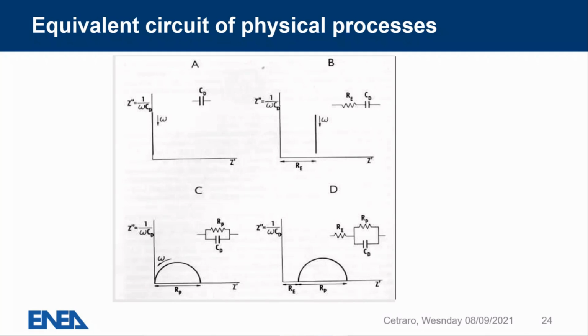It's important to say that if we apply a difference of potential changing in between, it happens that at low frequency we have the possibility for the capacitors to follow the charge and discharge, and so we will see that charge passes through this part, so with the bulk resistance and not the series resistance.